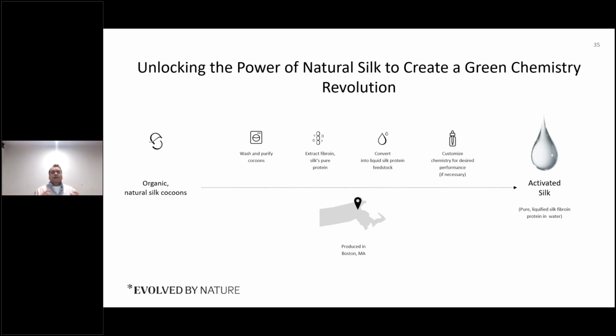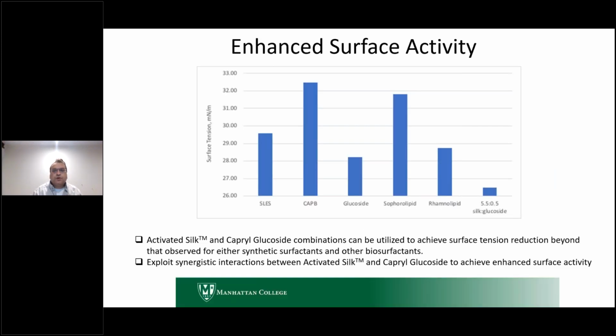So you have never brought these two materials together, and now you're going to explore a broad space of different ratios, pHs, electrolyte concentrations, all of these things. And again, this is where automation really helps to speed up that process. So for example, here, one of the things we wanted to do was to first optimize the surface activity between silk and this capryl glucoside, which is the bio-based surfactant that we were using. And here you see that we looked at SLES, CAP-B, glucoside by itself, the sophorolipid and rhamnolipids we discussed before. And then we saw, okay, how can we get to a surface tension value, between this mixture of silk and capryl glucoside, which actually beats all of these?